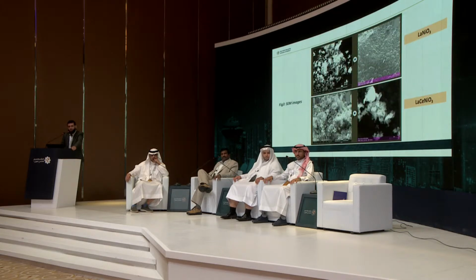These are the SEM morphological images, and in the case of lanthanum nickel perovskite, these catalysts showed a flake-like structure, and when we add ceria, this is a random porous structure.